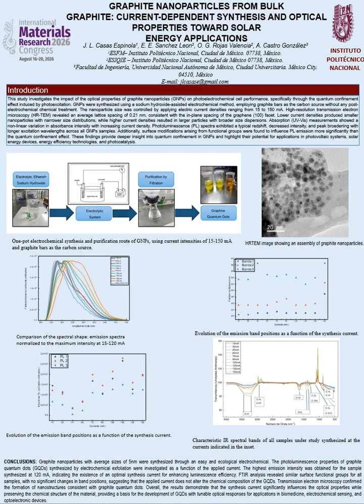The oxygen-containing functional groups and graphitic domains are consistent with the broad absorption band observed in the 330 to 400 nanometers region of the UV-Vis spectra. The band at 1580 cm^-1 corresponds to the C=C stretching vibration of sp2 hybridized carbon atoms, confirming the graphitic structure of the GNPs. This assignment is consistent with the UV-Vis analysis. The peaks identified in each sample are located at the same wave number, indicating that the surface states of the GNPs are essentially the same in each case.